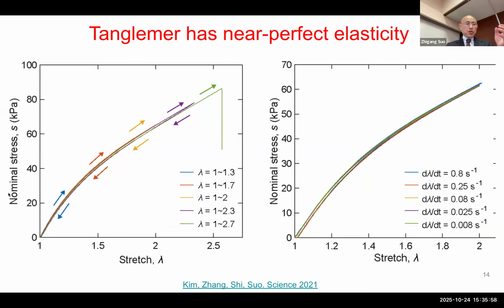We do a stress-strain curve. Stress is going up, and this is the stretch, how much you elongate. You can load up and load down. You see the hysteresis is negligible. So entanglement doesn't really increase hysteresis very much, negligible. Okay, very good. So hysteresis is good.